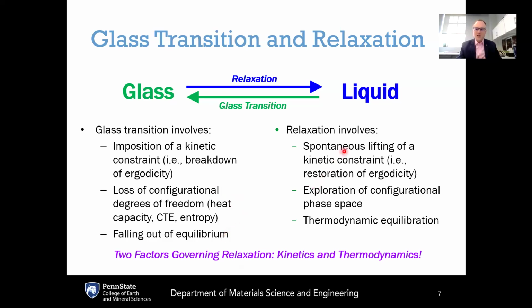The relaxation process is the opposite process. This is a spontaneous process that involves going from the glassy state to the supercooled liquid state. This is a spontaneous lifting of the kinetic constraint or a restoration of ergodicity, which is consistent with the ergodic hypothesis, stating that the system will become ergodic in the limit of long time scale.